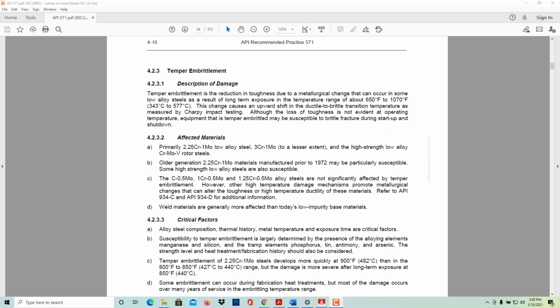Temper embrittlement. Temper embrittlement is a reduction of toughness due to the metallurgical change that can occur in some low alloy steels as a result of long-term exposure in the temperature range of about 650F to 1070F, 343C to 577C. This change causes an upward shift in the ductile to brittle transition temperature as measured by Charpy impact testing.